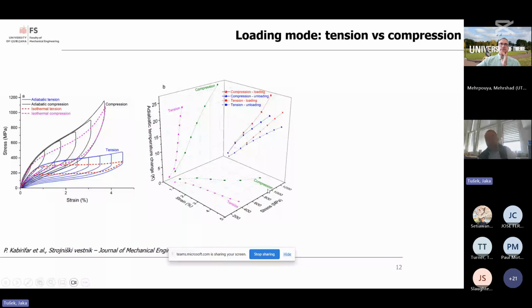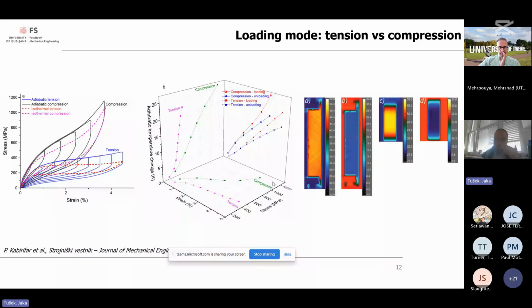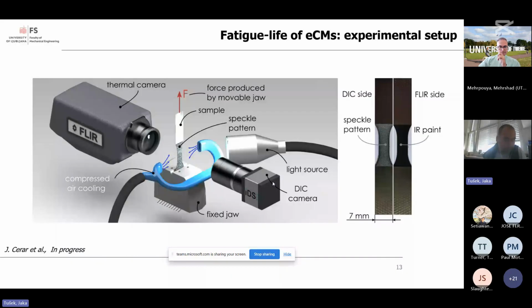The difference is also in the homogeneity of the elastocaloric effect over the sample. In tension, the transformation propagates through Lüders bands, which can be highly inhomogeneous, especially if only partial transformation is applied, while in compression, the transformation can be much more homogeneous, with a homogeneous distribution of the adiabatic temperature changes over the sample. In recent years, an important part of our work has been focused on studying fatigue and buckling of elastocaloric materials. We have developed a new experimental setup for comprehensive fatigue testing of elastocaloric materials, where the samples are monitored from one side with a thermal camera to measure temperature responses, and on the other side with a digital image correlation camera to measure the strain distribution over the samples.